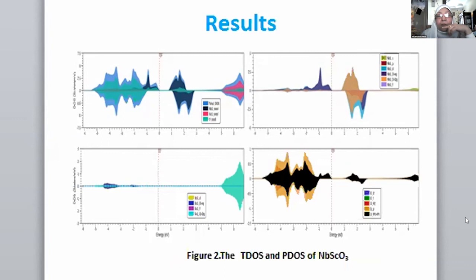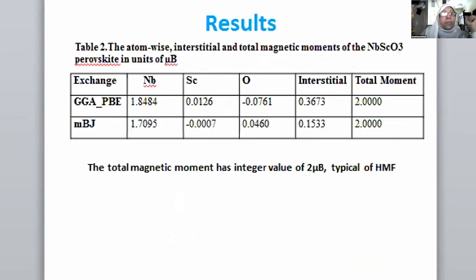And I remember that the niobium is contributing the D bands, because if I wanted to see the legend and to show you that the D bands are the maximum contribution from the niobium D bands. Then we are having here, of course, the oxygen. So mainly the niobium and the oxygen are contributing for the density of states. In the oxygen, we have the p orbitals, the py and the px orbitals that are contributing for the density of states.